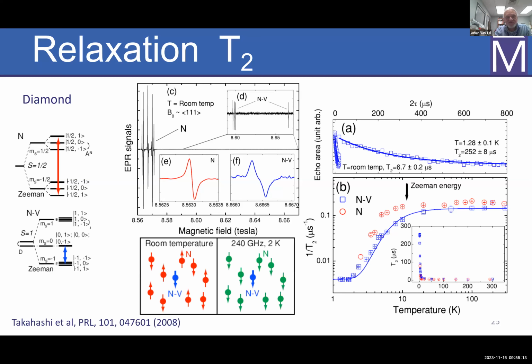So if you have a lot of pairs of spins in the neighborhood of the spins that you're looking at, and they can do flip-flops, this will change this spin's environment a bit and just induces a T2 relaxation. But now if all the spins are aligned the same way, there are no pairs that can do these flip-flops, and T2 gets longer. And of course, this is only true in high concentration systems where the electron spins themselves are important for the T2 relaxation.